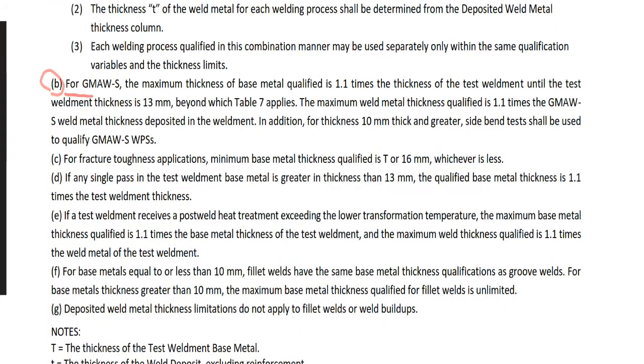B, for GMAWS, the maximum thickness of base metal qualified is 1.1 times the thickness of test weldment until the test weldment thickness is 13 mm, beyond which Table 7 applies. For GMAWS, S means short circuiting transfer mode. This kind of condition, GMAWS, is given in the actual CWI Part B questions. So you don't have to worry about what this GMAWS is. Just see this GMAWS in the given question. So when you see GMAWS, the maximum thickness of base metal qualified is 1.1 times the thickness of test weldment until the test weldment thickness is 13 millimeter. After 13 millimeter, Table 7 applies.